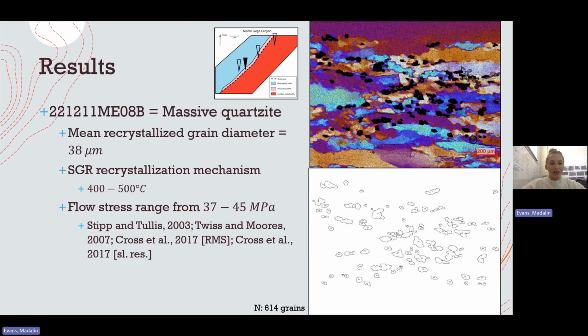The 08B sample is located in the massive quartzite and had a mean recrystallized grain diameter of 38 microns. It had a recrystallization mechanism that was similar to subgrain rotation, and in nature that has a temperature range between 400 to 500 degrees Celsius. The flow stress range for this one is between 37 to 45 megapascals.